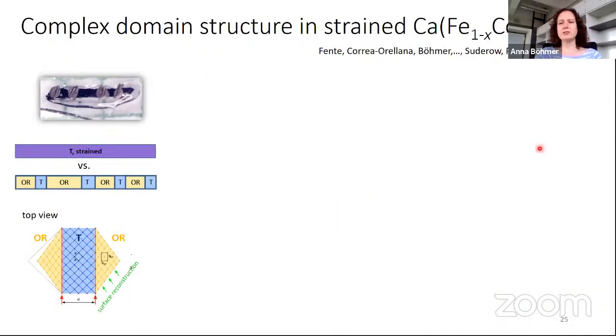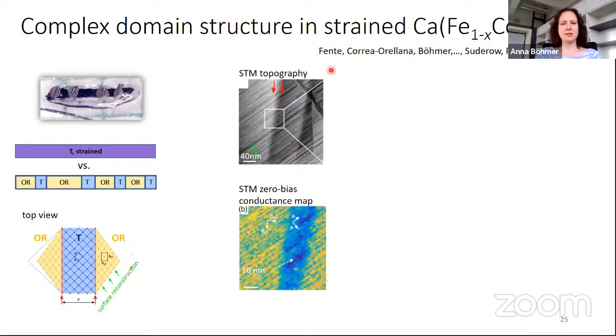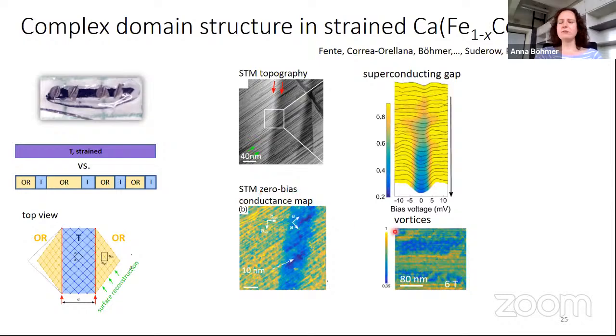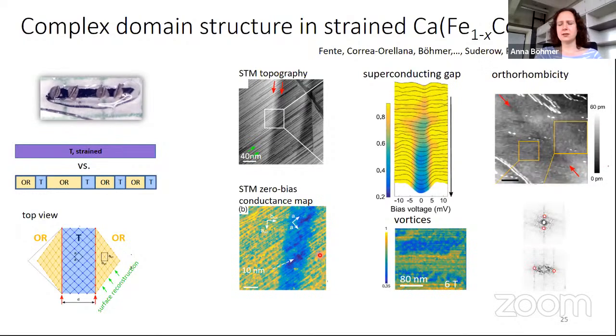And Hermann saw it together with Anton Fente in STM. So he looked at this and he sees different regions, and these will be these different regions. And if you want to know if it's a superconductor, you can do what's called spectroscopy, and from the spectrum you can see this region is really a superconductor, and the other one is not. You can also look at, is it a square lattice or is it a rectangular lattice? Did it go through the structural phase transition? And then some parts, actually, yes, they did.